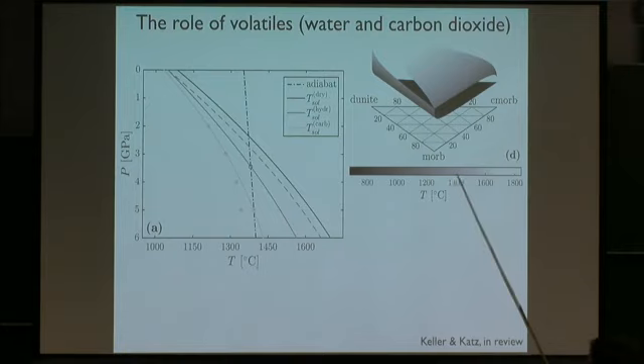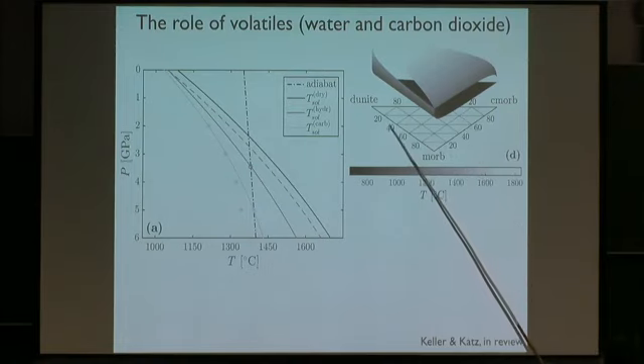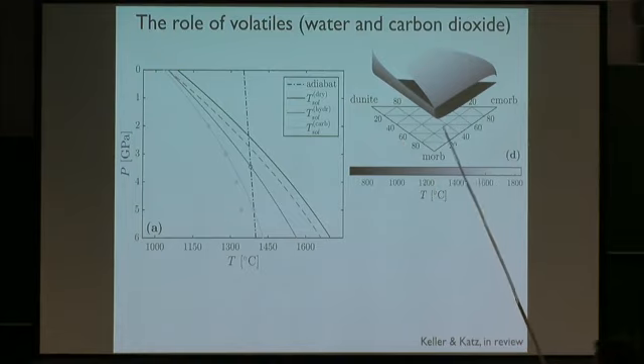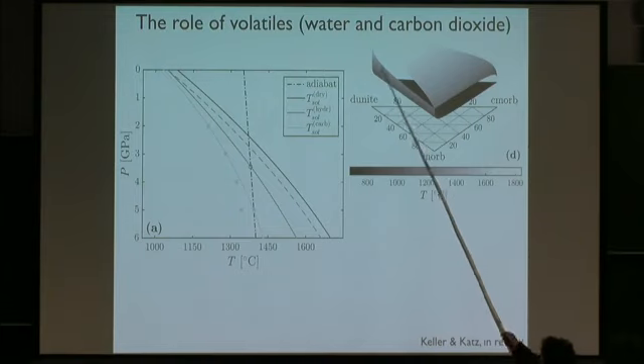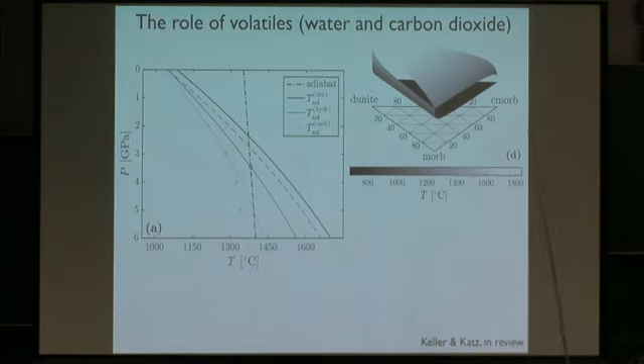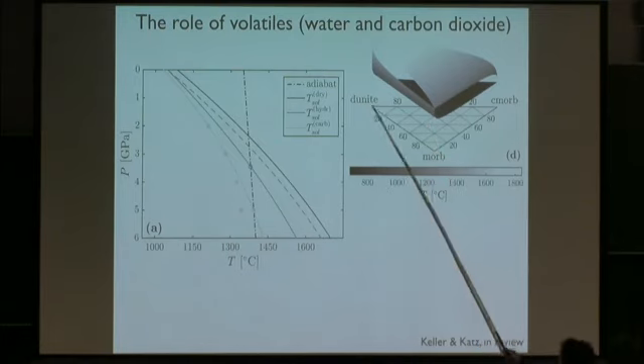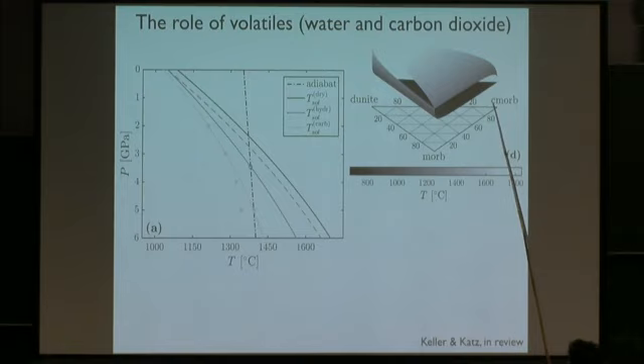So what we've done is to make the phase diagram a bit more sophisticated. Now we're in a ternary system, and his methods will scale up to 6 or more components. But we assume solid solution between all the components. This is like a dunite component. This is a MORB component, not after it's been erupted, but as part of the mantle. This is a little bit like what Ali has done in terms of analysis of the petrology of Iceland. We assume that there's some recycled component, and then there's some very refractory component. And then this is representing carbonated MORB.